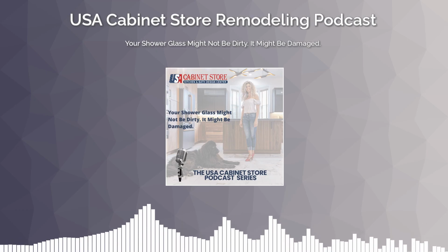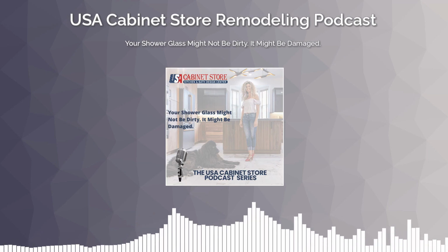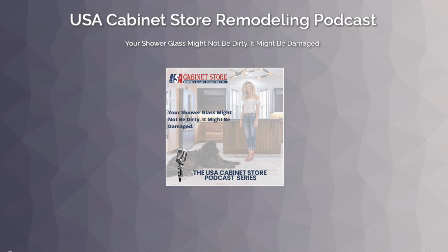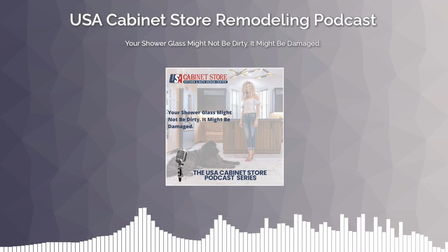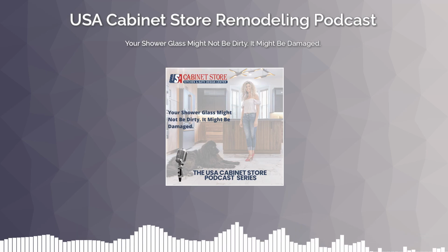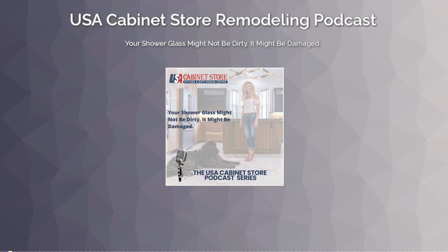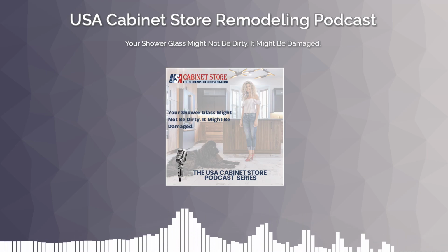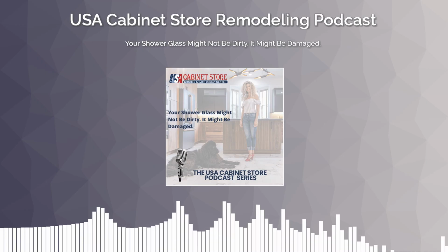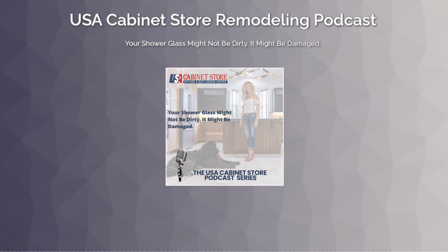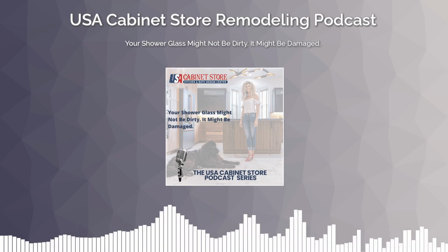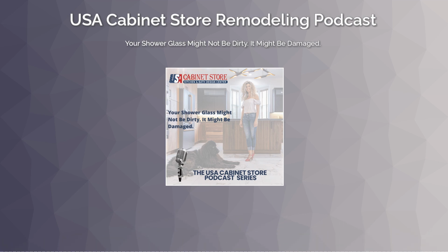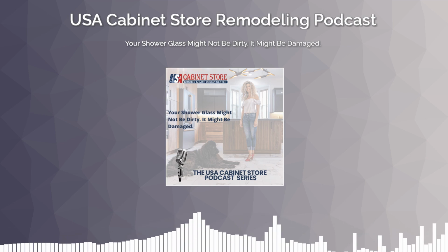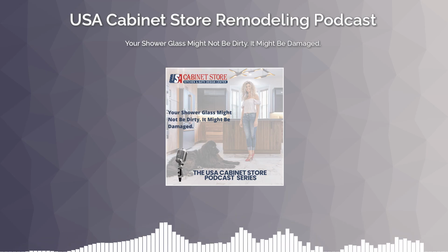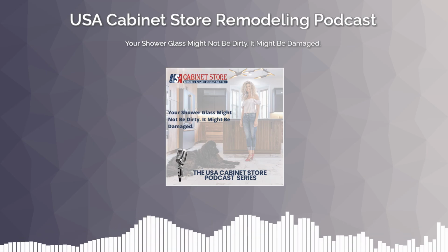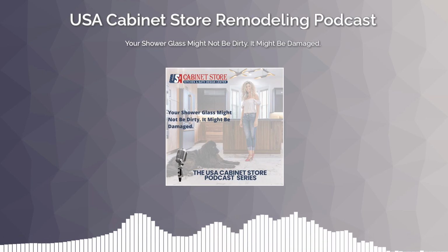Trapped water starts pulling sodium out of the glass. The sodium migrates into the droplet. And as it does, that droplet turns alkaline. Once its local pH goes past 9.0, it starts breaking the silicon-oxygen bonds that hold the glass together. So the water is literally dissolving the glass. Slowly, but yes. And the pitting that leaves behind is permanent. The restoration industry actually calls it shower glass cancer, which sounds dramatic, but the point stands. You cannot wash away a hole.